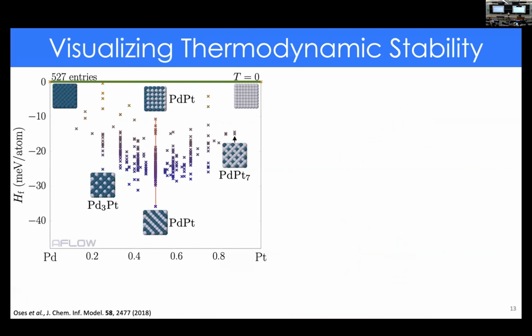I'm going to cover this quickly because we're going to go through it in the workshop, but I'm going to set it up as an example for how we found new materials. Here we have a plot of the energy versus composition. We're spanning alloys of palladium and platinum. At the 50-50 concentration, we have one type of structure that's half palladium, half platinum, and then we can have a different atomic arrangement. Think FCC, BCC, those different types of arrangements. And then we can also span the different compositions, the ratio of blue to white.